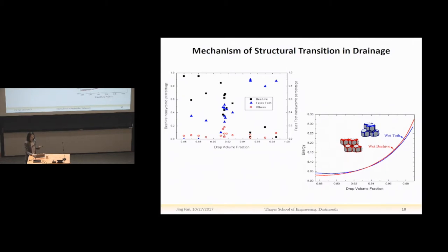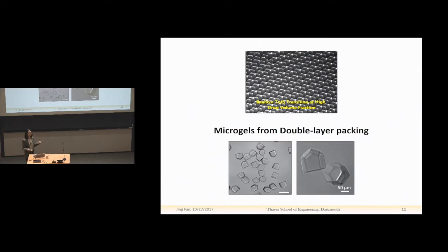So in the real emulsion system, actually both the surface energy and this structural instability are the two reasons that drive the structural transition. And within this two-layered system, if we polymerize the drops when they are deformed, we can get this structure, the microparticles.